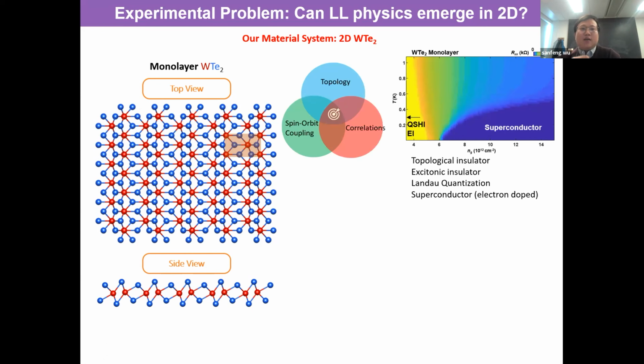So a single layer of tungsten ditelluride by itself is an insulator, which actually we do not fully understand what's going on in the insulating state. But we know it's a very strong insulator, and has been characterized as a quantum spin Hall insulator and also an excitonic insulator very recently. If you dope it, it becomes a superconductor, and so on. There are a lot of interesting properties in this material.